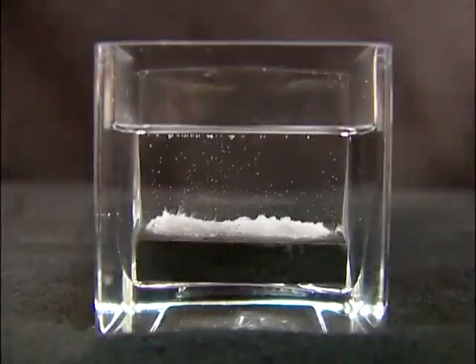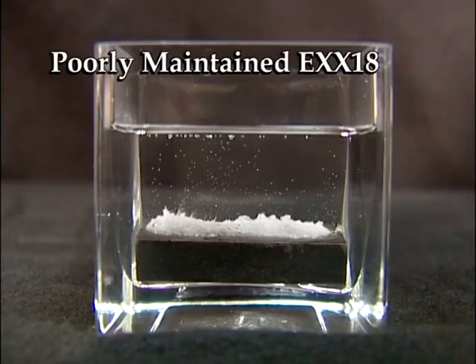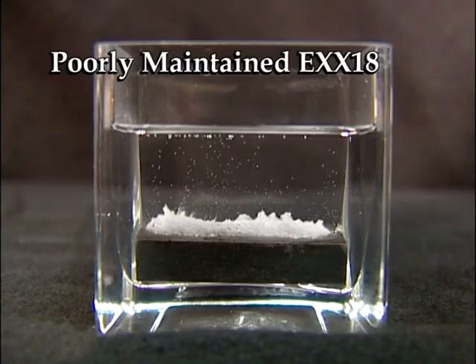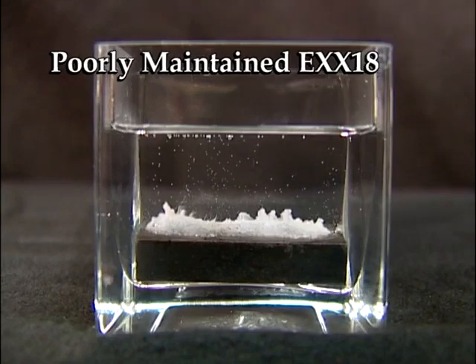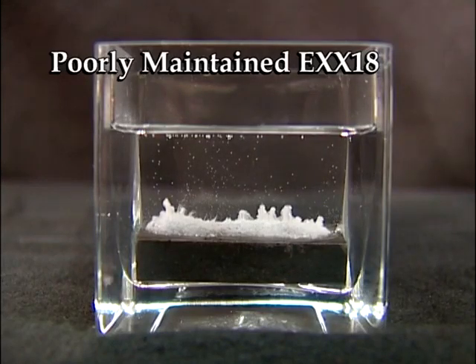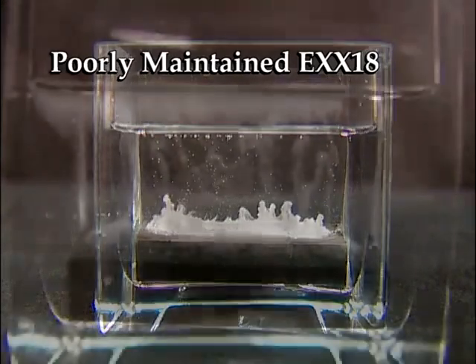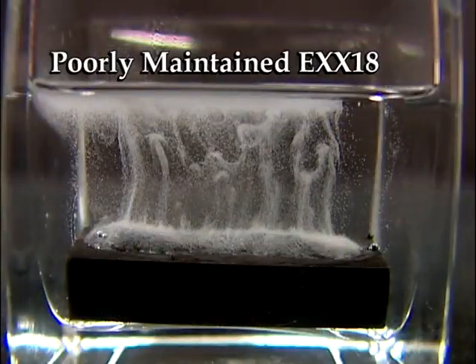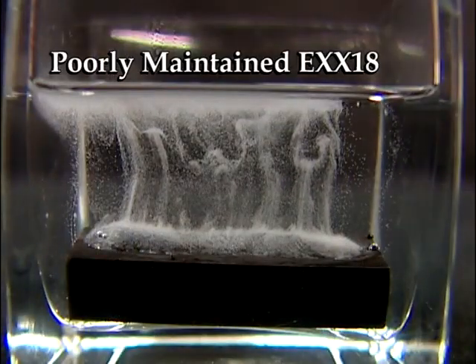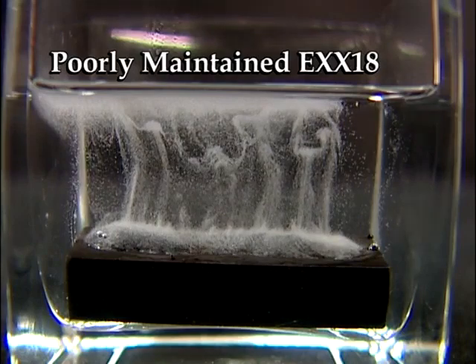The third sample was welded with a poorly maintained, low hydrogen electrode that was allowed to absorb moisture. Despite the moisture-resistant coating, we can see a large number of hydrogen bubbles diffusing from the weld, similar to the amount seen in the high hydrogen electrode.